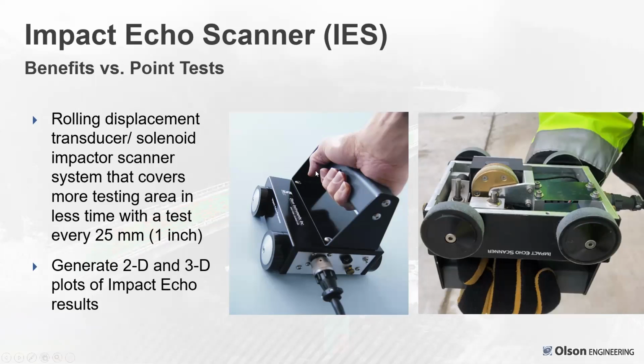So if you look at this, there's the handheld unit. You can also put it on a handle and roll it on a flat, smooth floor slab for profiling the thickness. The underside of this, though, shows the spring-loaded rolling displacement transducer wheel that every 1 inch, the sensor is lined up with the concrete, with one of two solenoids. You can select a smaller solenoid for most testing, typically up to 20 inches, or thicker concrete, up to maybe 40 inches, with a larger, heavier solenoid. And that's on a spring. So as you roll it, the timing is such that the solenoid will strike the concrete. This part's very similar to the handheld gauge, except that it's a point transducer, and you can select the solenoid, which is similar to this one in the handheld gauge.